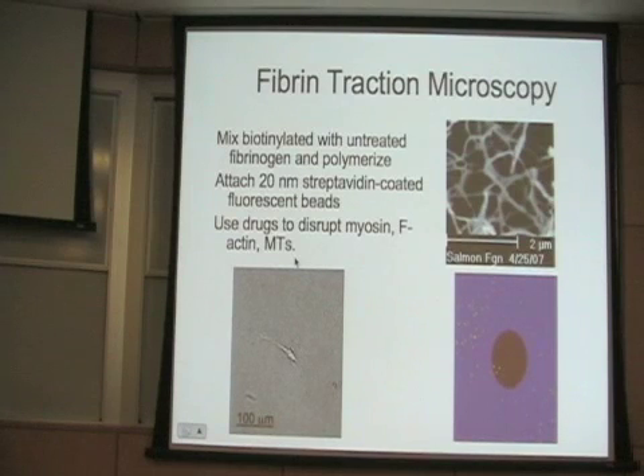So we've done very similar things to what we've already seen from traction mapping experiments for polyacrylamide, but we've done a very coarse-grained deformation map in these fiber networks. So here's an electron micrograph of the gels on top of which, or inside of which, these cells are put. This length scale is about 2 microns. This is a typical meshwork of a fibrin gel before the cells do their thing to it.